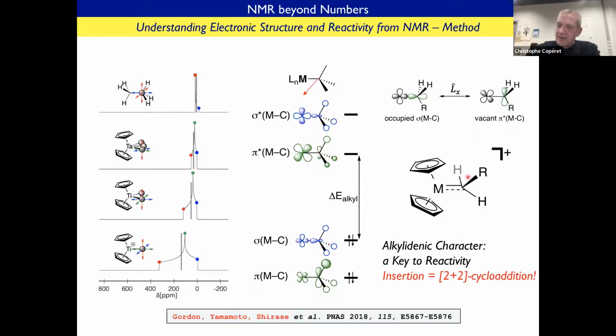in such a way that it creates this anisotropy and also very likely the reactivity. Which means that while we typically write a metal-carbon bond as a sigma bond, NMR spectroscopy tells you that the better way to write this molecule is that there must be a partial pi character in this metal-carbon bond that explains the NMR property, but very likely can also explain the chemical reactivity of this compound. Because as I told you, a compound that has this very large anisotropy is typically connected to chemical reactivity, in this case, olefin polymerization.